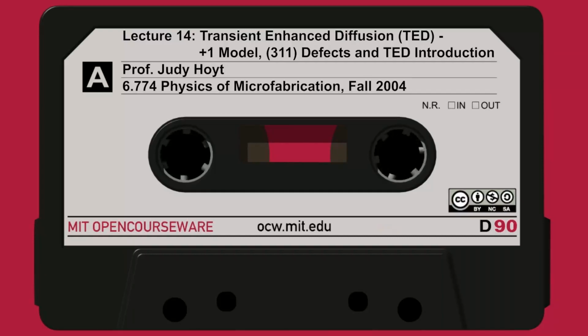What do we know about the diffusion mechanism of boron? Is it mostly interstitials, mostly vacancies, or both? Does anybody remember F sub I for boron? Well, let's take a vote. How many people think it's 1? F sub I. All right, yeah, it's 1. So what that means is the boron diffusion mechanism is almost entirely by interstitials, as opposed to diffusing with vacancies. So excess interstitials, boron needs interstitials around in order to move. That's its mechanism of moving.